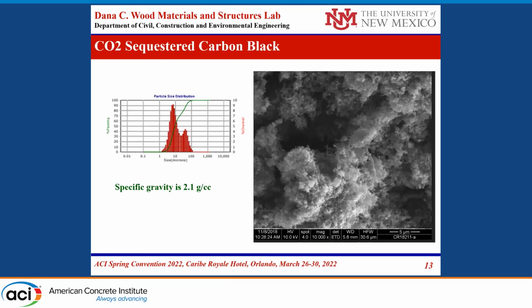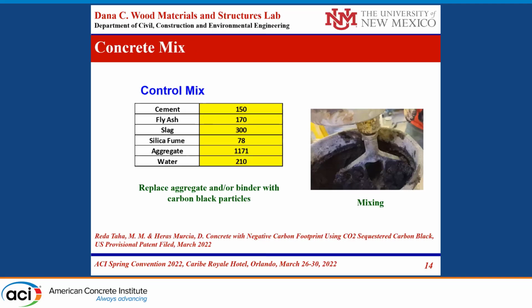So this is the specific gravity of this carbon black material, and some scanning electron microscope images of those carbon black particles. We decided to start with a simple concrete mix, and you can see one of the items we decided on in the standard concrete mix, even without the carbon black, is trying to reduce the amount of cement content. This is in kilograms per cubic meter. So we're reducing the cement and replacing a lot with fly ash, slag, and silica fume, trying to keep the binder fineness content as required for 3D printing, but in the meantime reducing the strength because you do not need as much in the case of sidewalks.